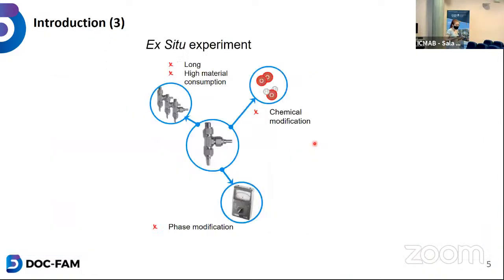To do my studies, I didn't use ex situ experiments because they take very long to process. You need to prepare several batteries. You need to stop them at different moments of your charge or discharge. And then you need to open them to recollect your electrode material and put it in the sample holder. So it's very long and time consuming, and you risk altering your phase because of contamination, for example, with moisture.